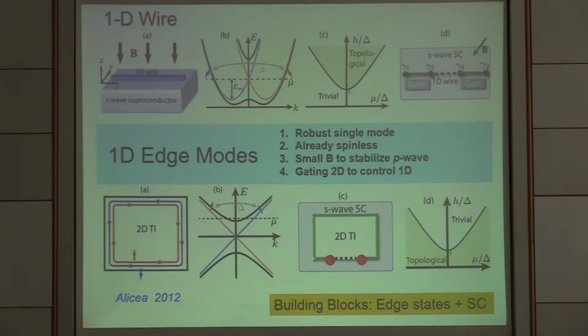So the motivation, of course, is that there are many interesting things to do with a 2D topological insulator. One of the motivations is to replace the 1D wire for realizing the Majorana boundary state. The advantage here, theoretically, is that this is a single mode, already spin polarized, and basically you don't need a magnetic field to generate the Zeeman splitting. And number 4, this material itself is two-dimensional, but the active part, which is one-dimensional, is controlled by gating in the two-dimensional case.